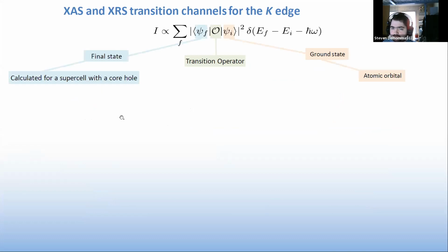We just need to calculate, in fact, their intensity, which is proportional to this kind of Fermi's golden rule. That is to say, the transition probability from a ground state that you can see here to a final state, both states being coupled by a transition operator, which depends on which spectroscopy technique we are using, that is to say, which light-matter interaction is at play. Here, the final state is calculated with a core hole, and so the core hole must be isolated in a supercell. And the ground state is just a classic atomic orbital.